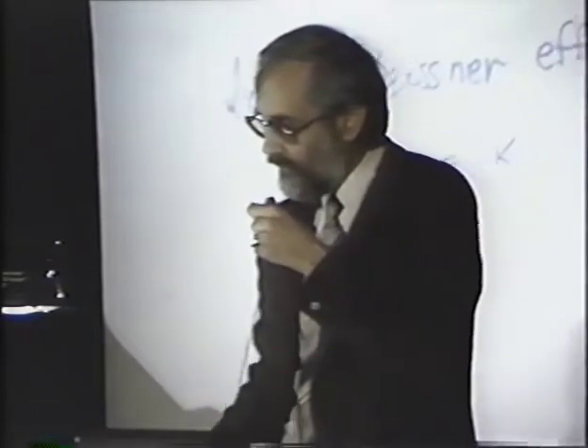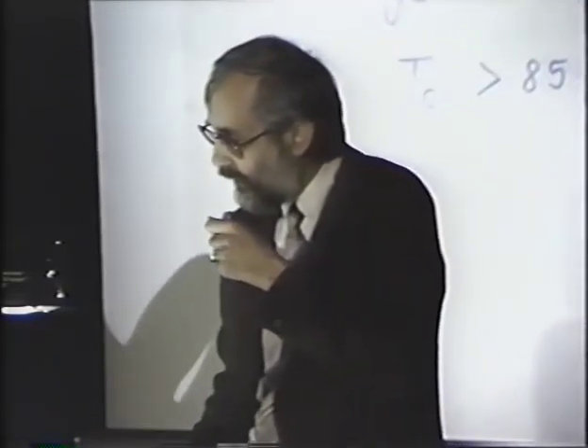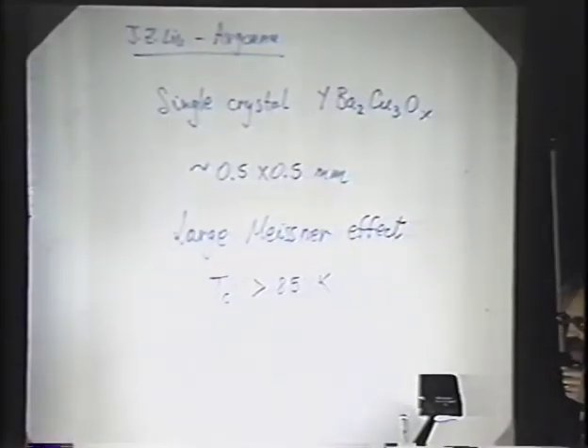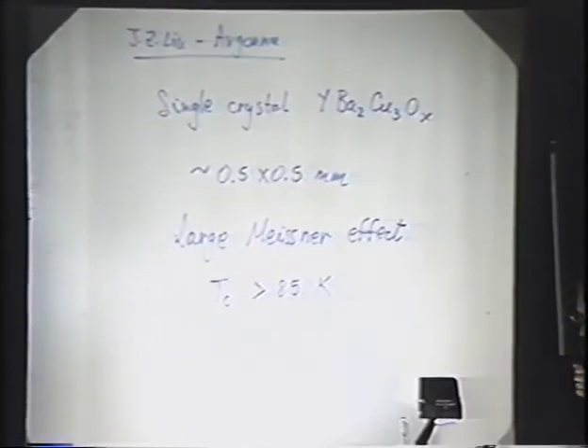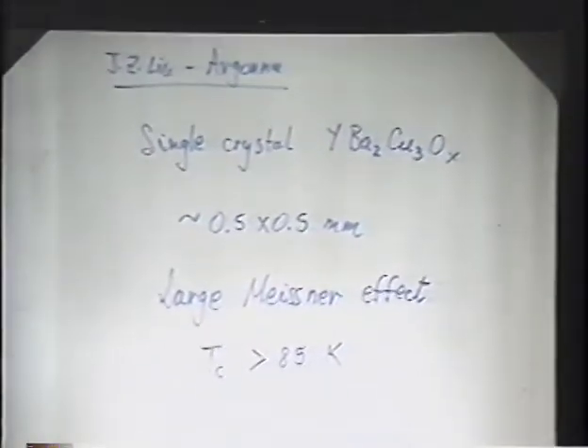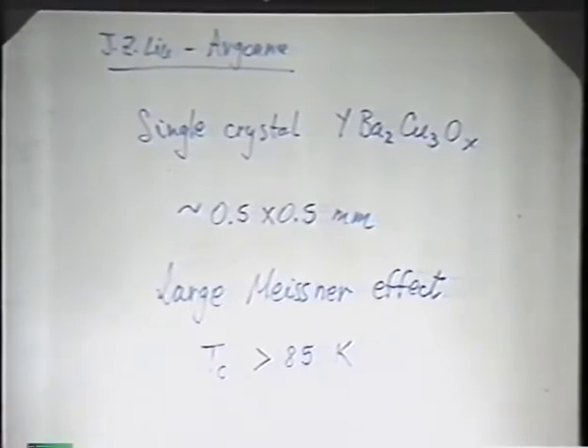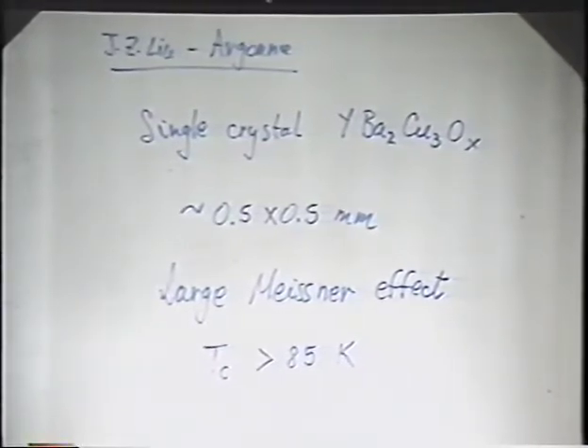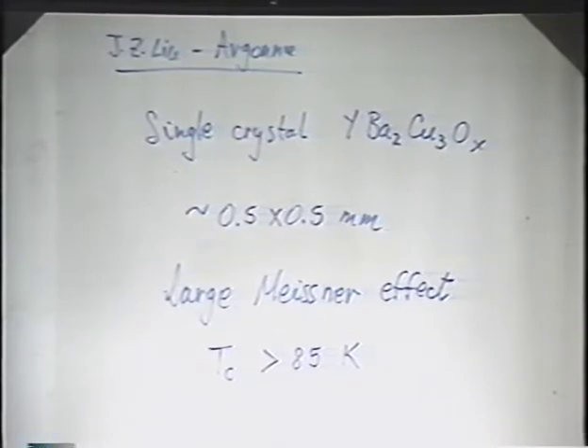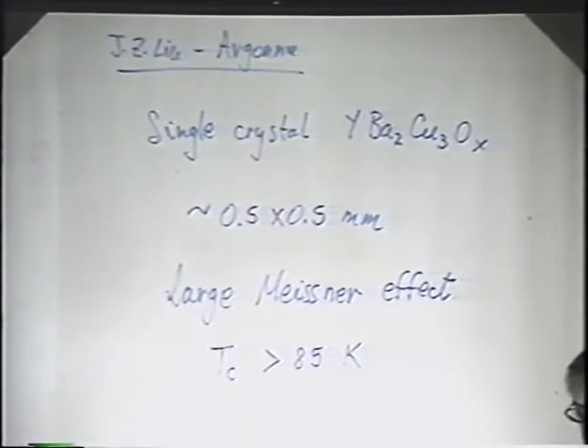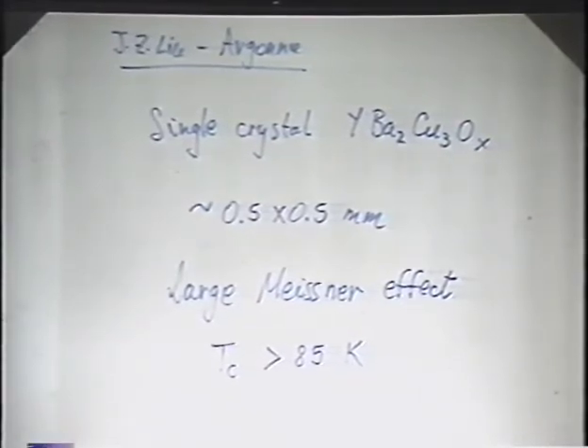And then finally, as of 2 days ago, we do have a single crystal of yttrium, barium 2, copper 3, oxygen. Roughly half millimeter by half millimeter crystals have been made. They have large Meissner effects approaching 100%. The data is a little sloppy at the moment because it's under process, and I've been working by telephone, but it certainly has critical temperatures in excess of 85 degrees.